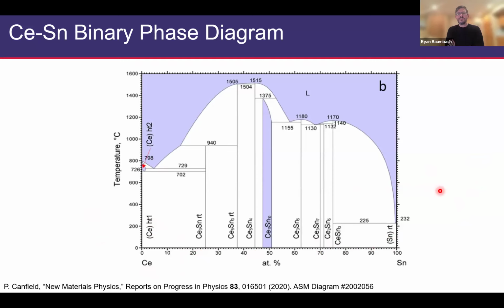I do want to point out that there are other combinations, not of cerium and tin, but of other elements, that have absolutely no phases in them. In other words, no bonding occurs. And this on its own immediately gives you some insight when you're thinking about whether or not a particular thing that you want to grow will actually form. It might be a problem if there are just a tremendous number of binary phases that want to form. In other words, there are all sorts of energy minima that can produce these compounds that might circumvent your ability to produce the thing that you want to make. On the other hand, if there's absolutely nothing that forms in the space, maybe you can put this to work to your advantage, but it also might just mean that the combination that you're after really is not one that's going to form because those elements don't play nicely together.